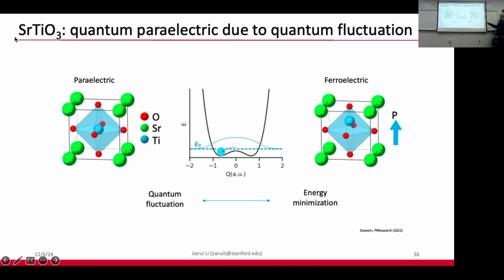Like in barium titanate, it has a very interesting phenomenon that as you cool down, they will first develop along these directions, and then it rotates to 1-1-1, and then rotates to 1-1-0 as a function of temperature. So it's possible. They're very close to each other in the minimum energy. So my understanding is that basically the strain stabilizes the metastable state.